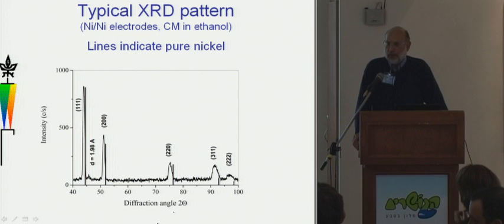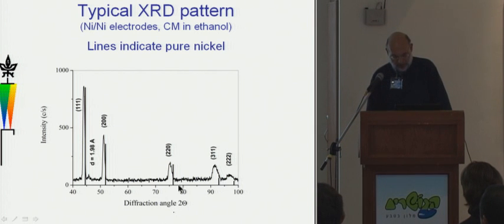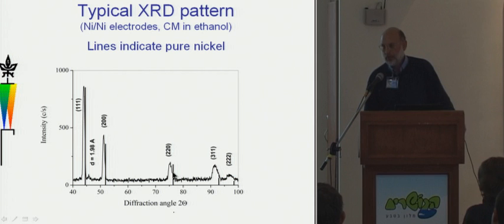This is an X-ray diffraction pattern of powder that was produced, contact mode between two nickel electrodes operating in alcohol. The vertical lines show the bulk diffractogram from pure crystalline nickel. What we see is that adjacent but displaced from each line is in fact the line that we measure. There are two things that are significant here. First of all, of course, the peaks are broadened, and this is characteristic of small crystallites. But the other is the displacement.